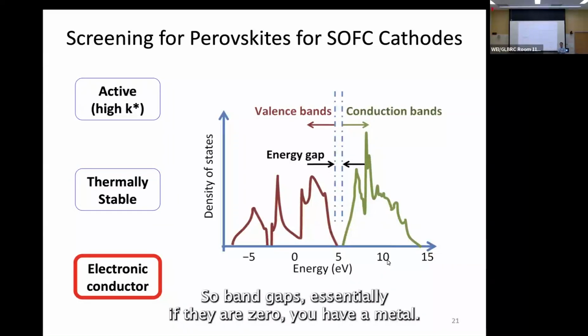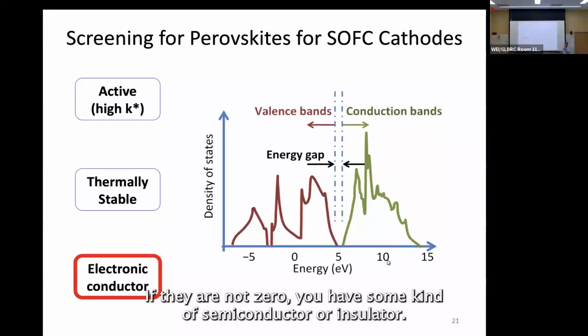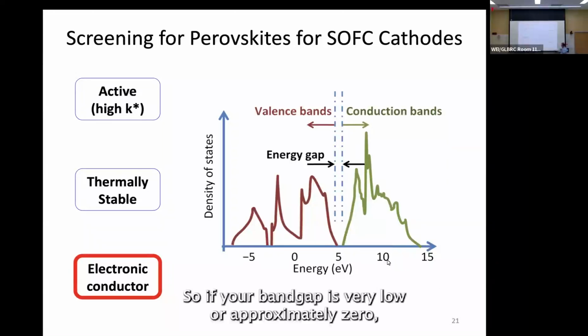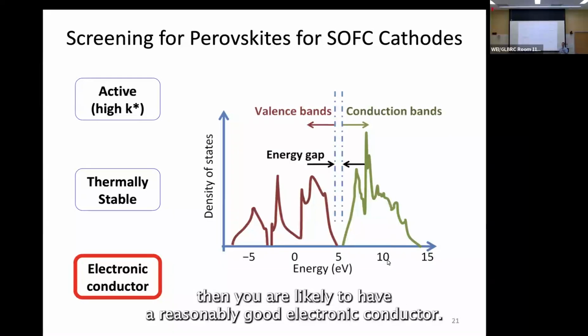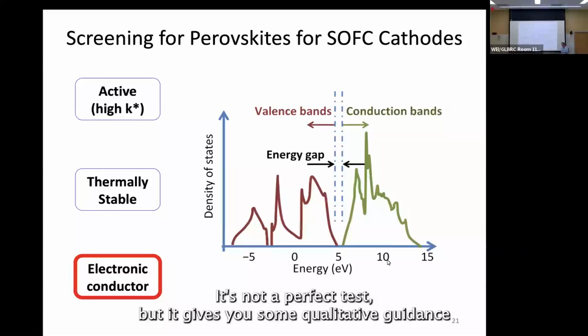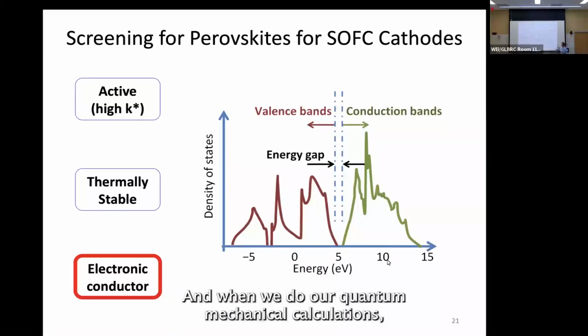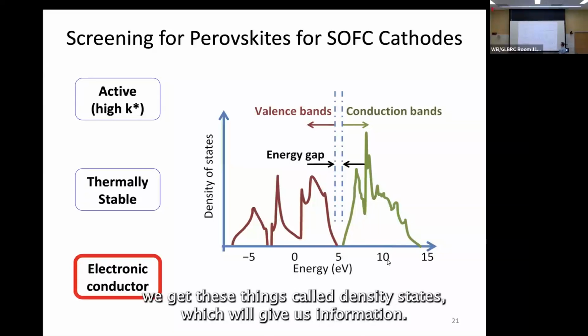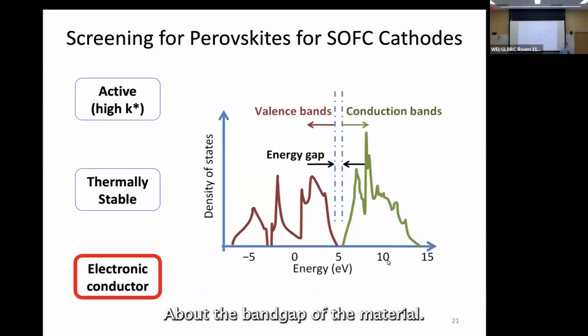And we can calculate the band gap of the material. So band gaps, essentially, if they are zero, you have a metal. If they are not zero, you have some kind of semiconductor or insulator. So if your band gap is very low or approximately zero, then you are likely to have a reasonably good electronic conductor. It's not a perfect test, but it gives you some qualitative guidance that you're likely to have a good electronic conductor. And when we do our quantum mechanical calculations, we get these things called densities of states, which will give us information about the band gap of the material.